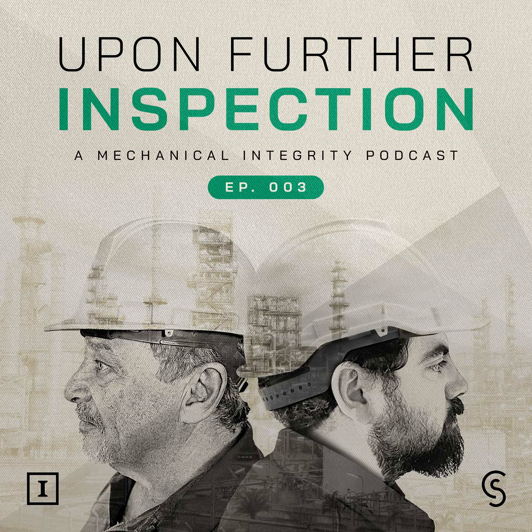And then we went through a phase of looking at what we call fine line steels, because a lot of the HIC-SOHIC was being initiated by inclusions in the steel. And these were typically microscopic sulfur voids, or it could be an actual microscopic bubble in the steel, because with HIC-SOHIC, you've got a corrosion reaction occurring at the surface of the steel that's allowing hydrogen to go through the steel to collect at those sulfur inclusions or voids that might be in the steel. So the industry even started producing this steel called fine line steels. And then we did laboratory testing on, okay, what are we seeing now with the fine line steels?